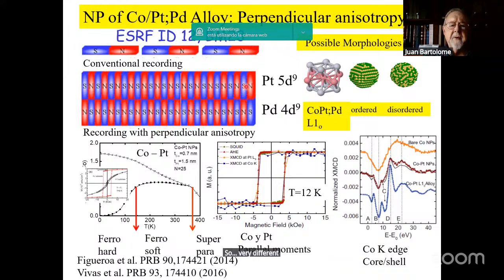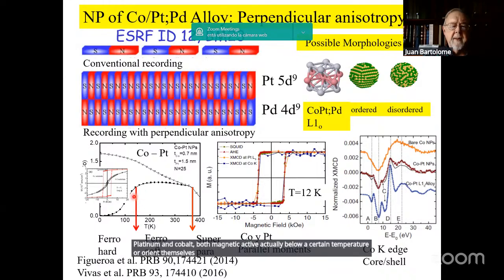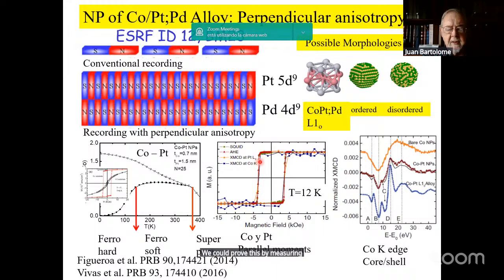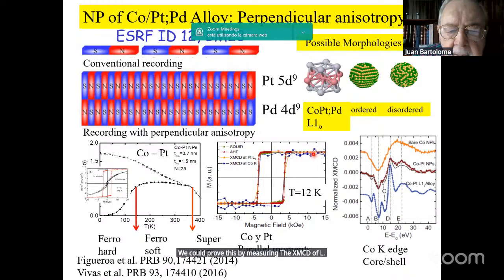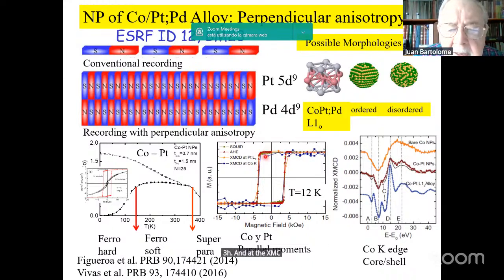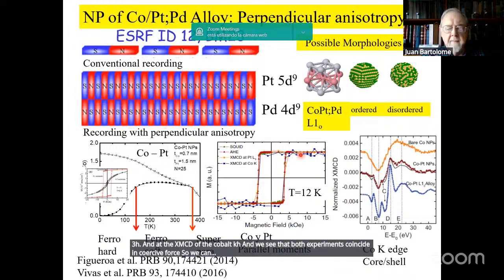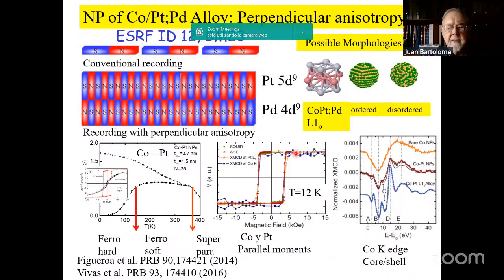So very different to what we have seen so far. Platinum and cobalt, both magnetically active, actually below a certain temperature orient themselves in a ferromagnetic way, and below about 150 Kelvin they are hard ferromagnet oriented. We could prove this by measuring the XMCD at the platinum L3 edge and the XMCD at the cobalt K edge, and we see that both experiments coincide in coercive force, so we are showing that both are collinear in this range of temperature, and they support a strong hysteresis curve,